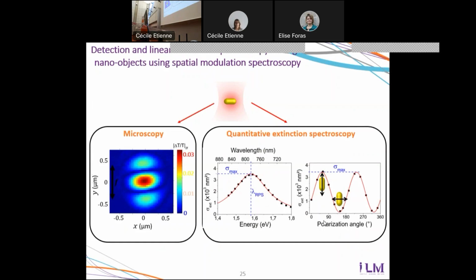And then we can also perform spectroscopy, that is focused on one nanoparticle and measure its extinction spectrum as a function of wavelengths. And so here that's the spectrum of a metal nanoparticle, a gold nanorod. It shows a resonance near 800 nanometer wavelengths. And we can also measure this as a function of polarization. So here, also for a gold nanorod, since the object is very elongated, its response is not the same for all polarizations. It's maximal when the polarization is aligned with the rod axis, and it's minimal when the polarization is transverse to the rod direction.